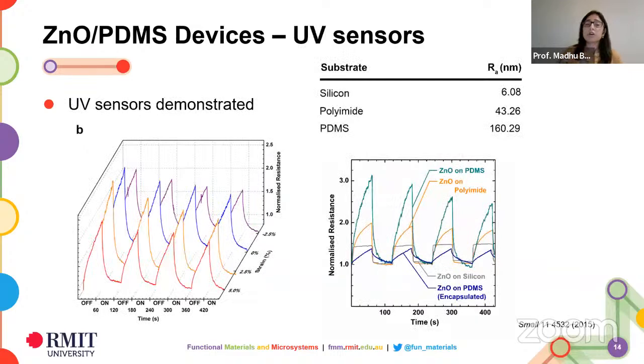You can also use zinc oxide as a UV sensor. So if you take the transmission characteristics of zinc oxide, you will find it's really sensitive in the UV region of the spectrum. And you can see over here, it performs exceedingly well as a UV sensor as well. So it almost reacts in a matter of seconds, and then it recovers in a matter of seconds.